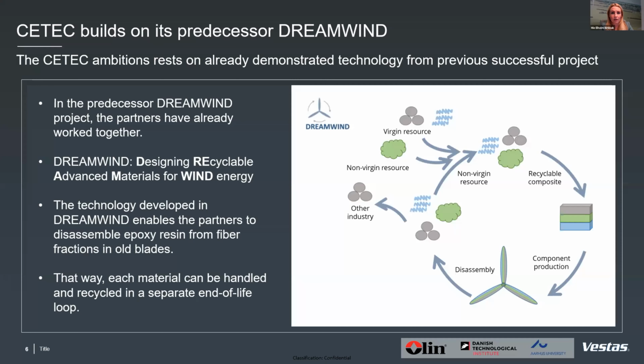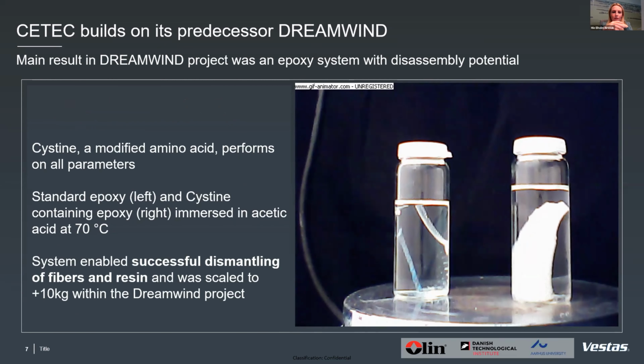And we already did a lot of this work in the predecessor DREAMWIND project, where we demonstrated that by making a small adjustment to the epoxy formula, we can basically dissolve it at the end of life. And that also means that we can dissolve the entire composite structure and then handle the resin part and the fiber part separately.